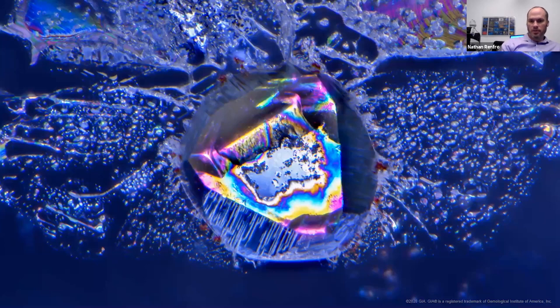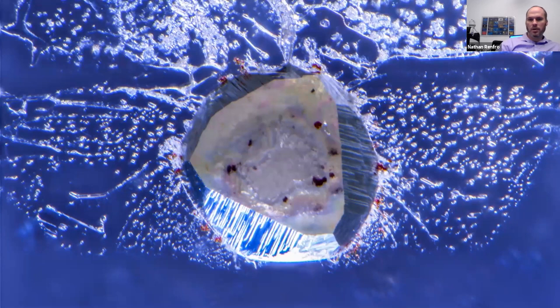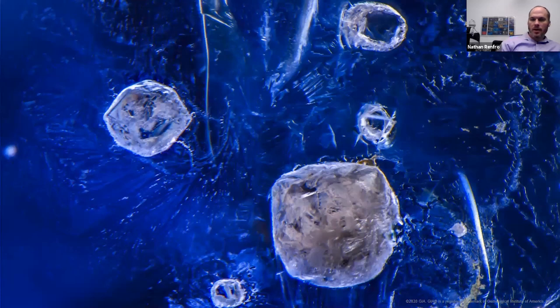When inclusions are present, this negative crystal here is filled with calcite and carbonate minerals. Using a little different light, we see a whitish core component and then a rind of a different mineral — a calcite core with an alkali rind in this negative crystal. And just like we saw in Dry Cottonwood Creek, Yogo sapphires can also have garnets — they're a unique chemistry garnet, a mixture of pyrope, almandine, and grossular. Not a combination of garnet chemistry you would normally see in a facetable gem garnet.